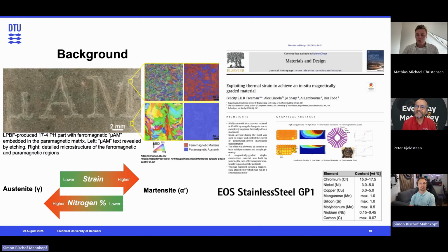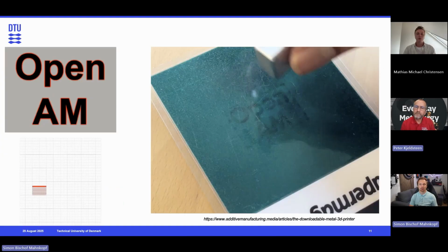And traditionally, when doing these kind of prints, as you create these parts where you want to have two different phases, we call those functional graded materials. When doing these two different zones, in a traditional printer slicer, you would have to have two different objects in order to have two sets of process parameters. But what we could do is we had an open platform, so we could create our own slicing, where instead of just having one set of process parameters per object, we could vary it per layer or even for one scan line. So in the middle of doing a single laser scan line, we could actually just ramp up the power or ramp down the scan speed to get local higher energy.